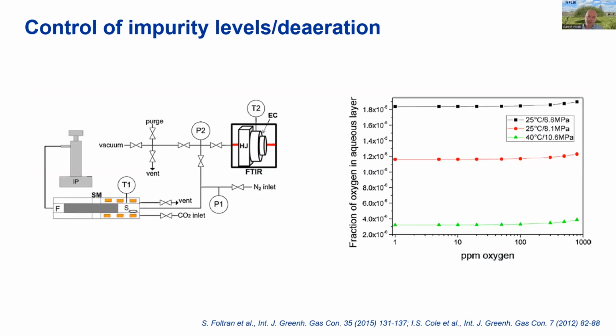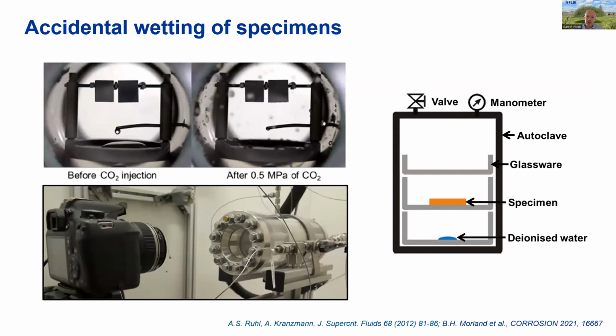So I'm just going to mention briefly some of these problems and how they could be addressed. With control of impurities, it's really important to measure the impurity levels. This is typically done using spectroscopic or analytical techniques on the outlet of the autoclave to make sure that impurity levels aren't being depleted during the test. From the accidental wetting point of view, these are some nice pictures from IFE that show the splashing of water on the test specimens. What you can do about it is to separate physically the specimens from the liquid water so that any splashing that occurs doesn't actually impact on the specimens. But not every lab does this.